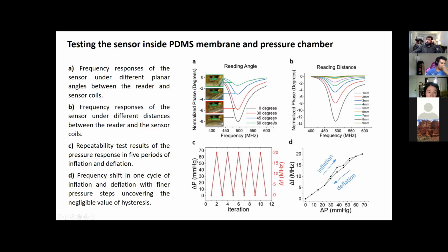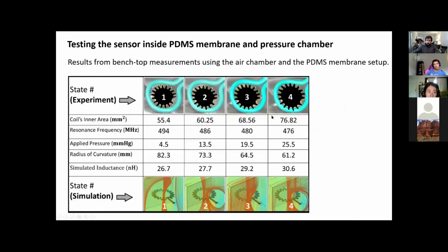So when you have a contact lens on and you look left and right, the plane of the sensor and the plane of the reading coil are going to have an angle that changes a little bit. And I did some extreme tests, like 30, 45, 60 degrees. And I also realized that by changing the angle, again, the strength of the signal changes, but not the resonance frequency. So these are really good control experiments that show that it was encouraging, because we also had the same concern you just mentioned.